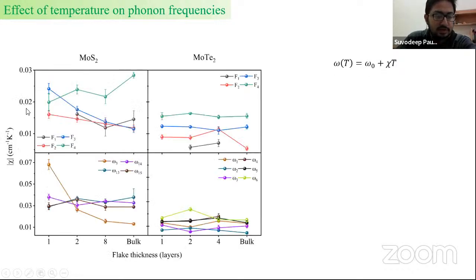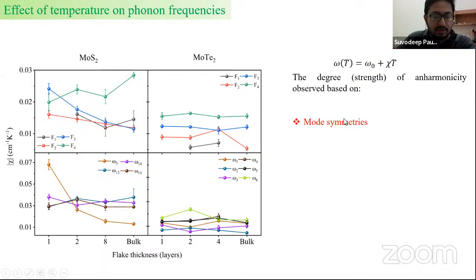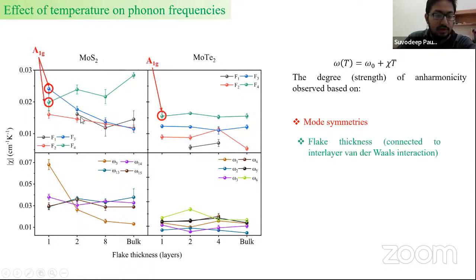We see that the strength of anharmonicity has intricate dependence on two factors. The one is mode symmetry. So for a particular thickness, depending on the different phonon symmetries, we get to see different extents of anharmonicity. For example, the A1G mode for both MoS2 and MoTe2 shows a stronger anharmonic behavior compared to the E2G modes here, which are in-plane modes.